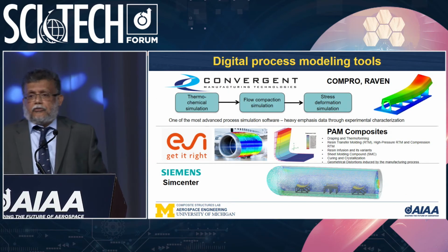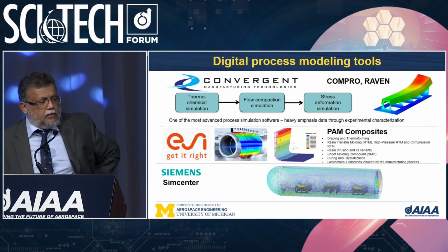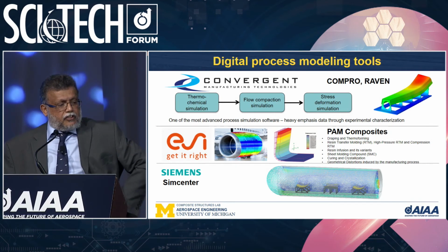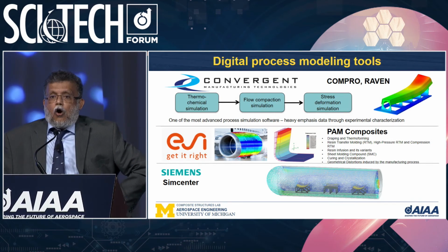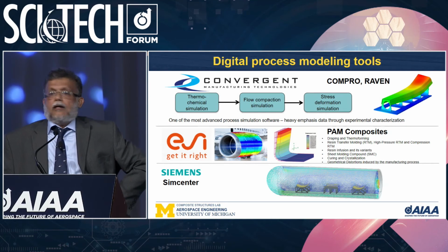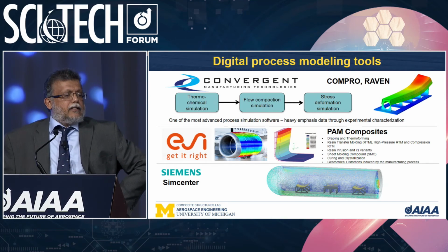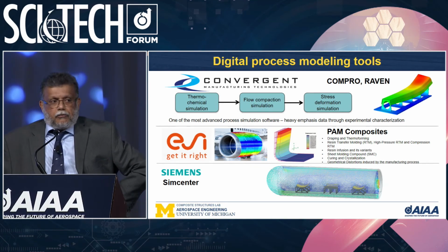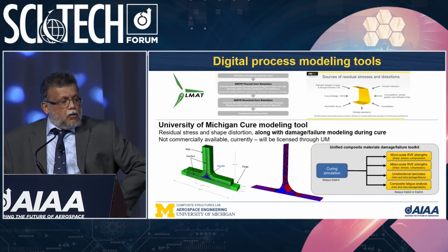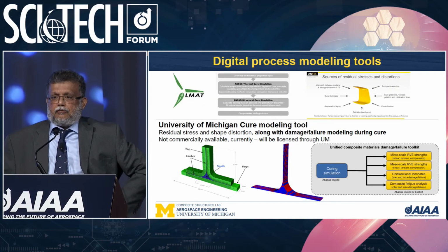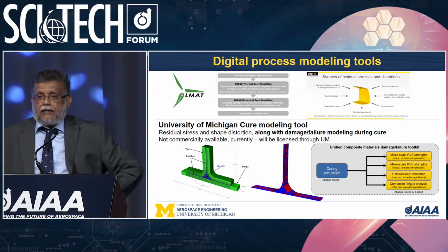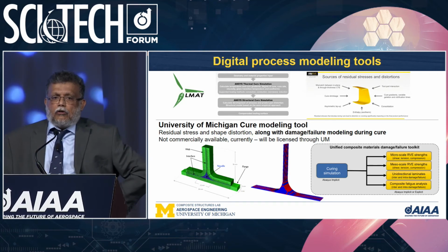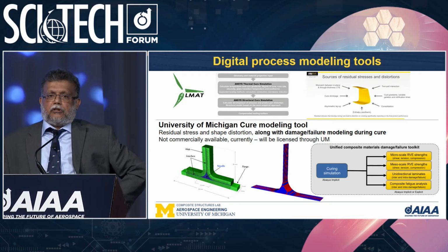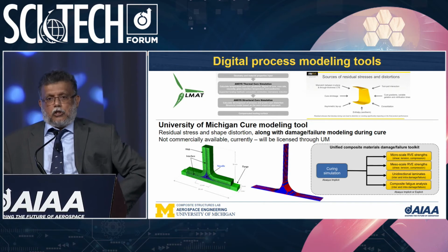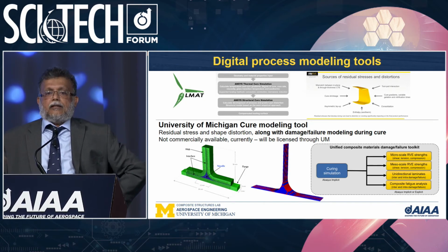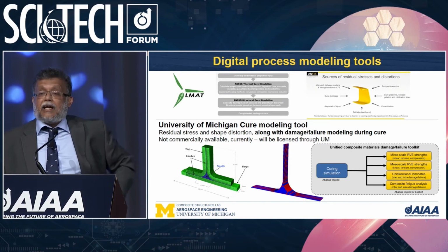Now, there are many tools that are out there: Convergent, PAM Composites, Siemens, ESI. All these tools provide residual stress and distortion of a part during the cure cycle. What we've done at the University of Michigan is we have a tool that does all of that, but in addition, it can also predict damage evolution during and after cure—during the cure, and then after, when you subject it to mechanical loading.